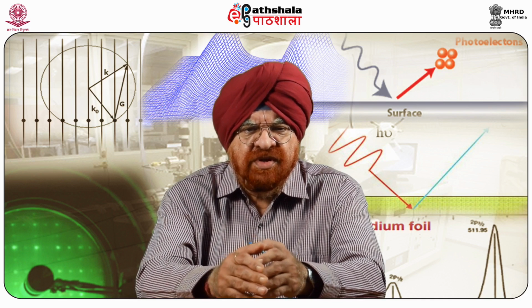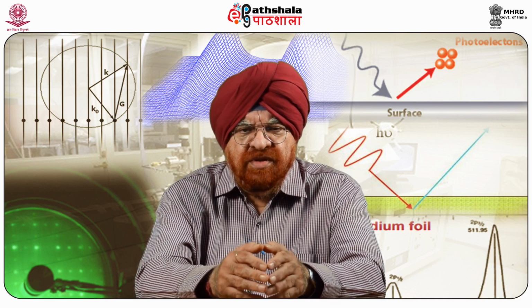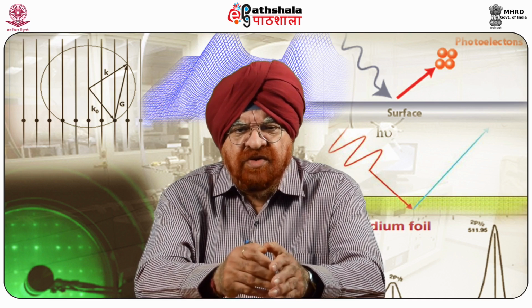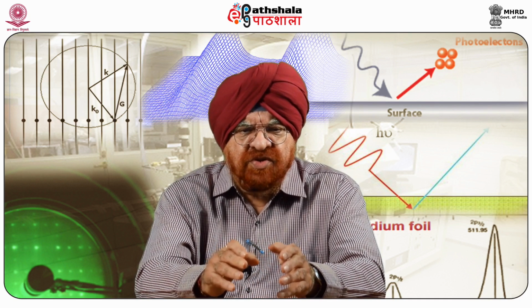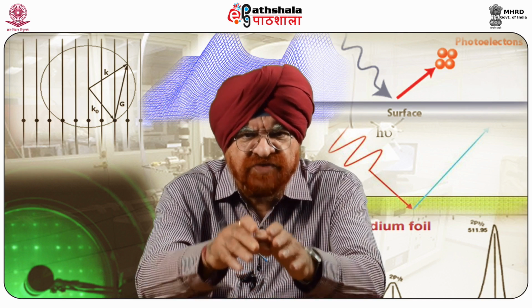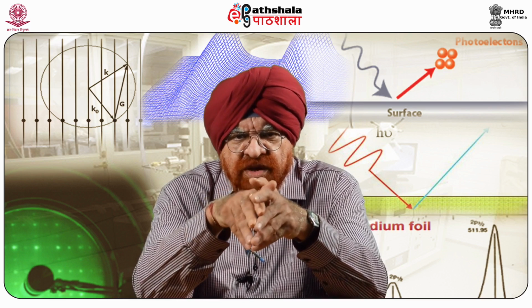Though the calculations could be sped up by the use of symmetry-adapted functions in the angular momentum expansion, this remains fatal for the retrieval of the correct values of structure parameters when a scan of the parameter space is used to find the best theory-experiment fit in a trial and error procedure. This is because the number of trial structures grows exponentially with the dimensionality of the parameter space, that is, the complexity of the structures. Therefore, the strategy to solve complex structures by LEED must be twofold.